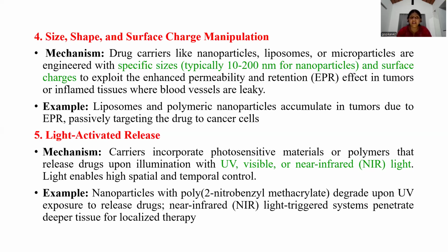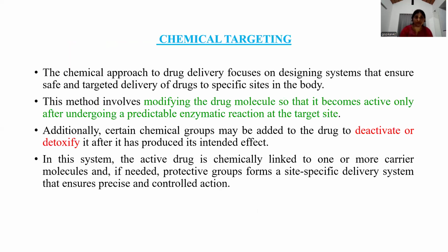And next is the light activated release, where the carriers incorporate photosensitive materials or polymers that release drug upon illumination with UV, visible or infrared light. Light enables high spatial and temporal control. Examples include nanoparticles with poly o-nitrobenzyl methacrylate that degrade upon UV exposure to release the drugs, and near infrared light triggered systems penetrate deeper tissue for localized therapy.